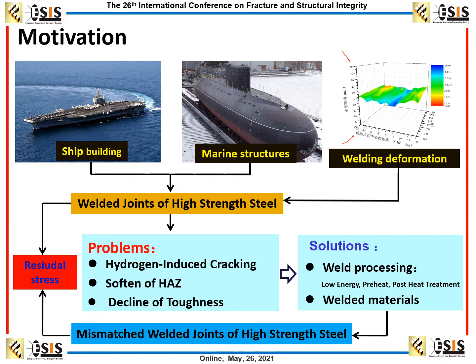It is very important for the structure service under some special conditions. For the welded joint of high-strength steel, there are some problems such as hydrogen induced cracking, softening of the HAZ, and decline of toughness. So we can use some different solutions to solve these problems. One direction is about the welding processing, like using lower energy, or doing preheating treatment or post-heat treatment. Another strategy is using different welding materials, like mismatched materials.